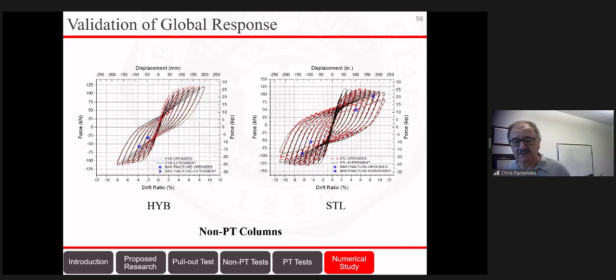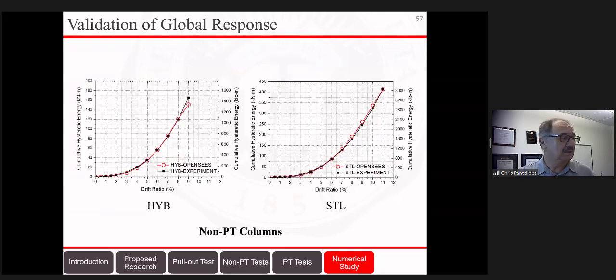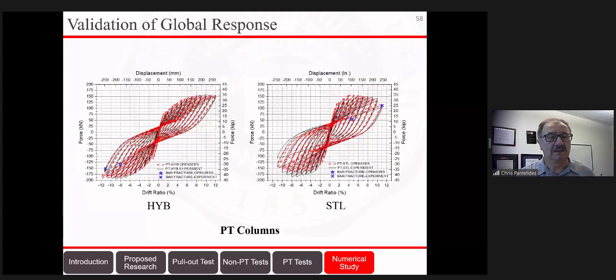For the steel column, we're very close. We're within 1% as far as the maximum load. And again, the model breaks down when a bar fractures. As far as the hysteretic energy, you can see we're very close. We're within 5% for the hybrid column on the left and about 10% for the steel column on the right.